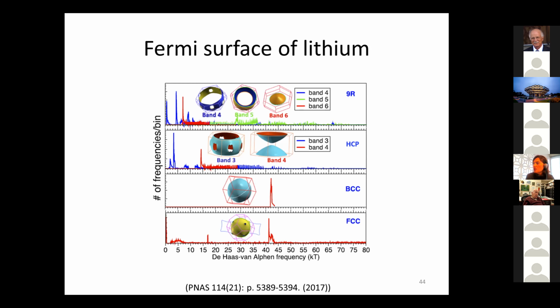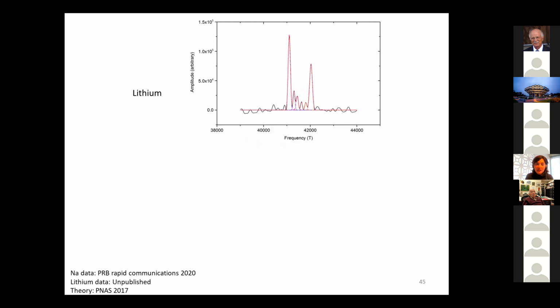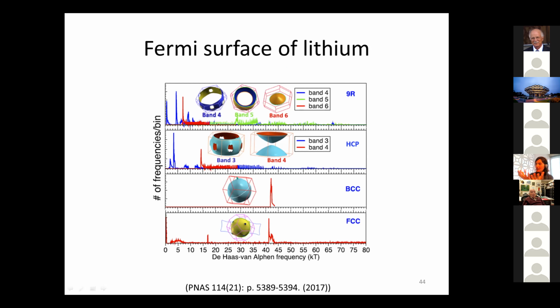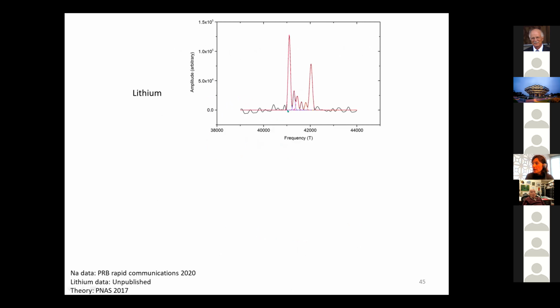The problem is that these studies are so difficult on lithium. Lithium is very soft, it distorts very much, and the presence of this martensitic transition makes the fermiology experiments extremely difficult. So the latest experiments go back to the late 1990s, so we needed to revisit these experiments, and that's what we did on the experimental side of things. And this is the fermiology. This peak that you're seeing is telling us the location of this spherical part of the Fermi surface, and you see it's split, it's anisotropic. So we see by experiments that we have done in the high magnetic field lab that there is a splitting.